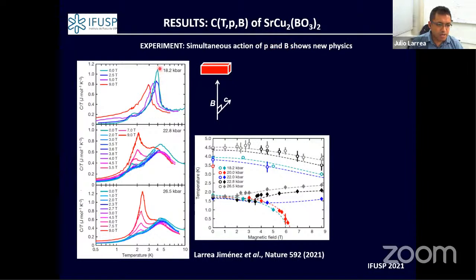We take this sharp peak at 18 kilobar and started to apply magnetic field. What you observe from the experiment is that by application of magnetic field, this sharp peak started to decrease. The position at temperature for each field is plotted in this curve. For 18.2 kilobar, this is the turquoise color here.